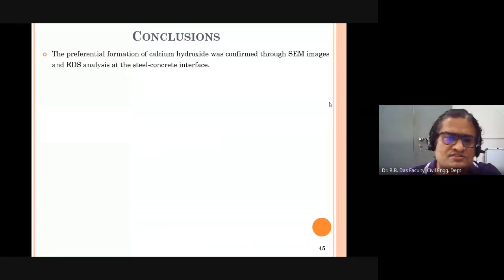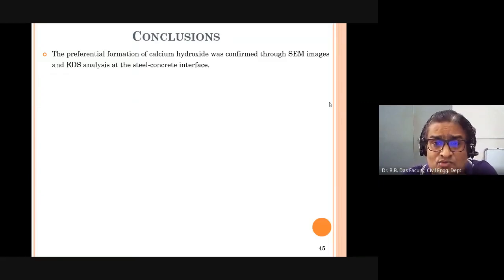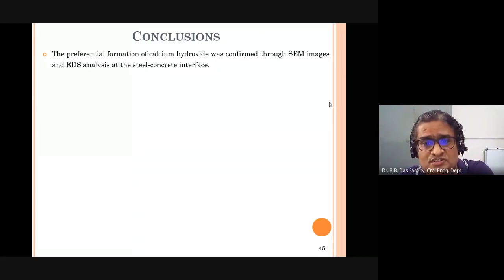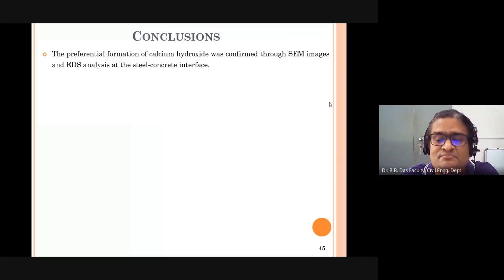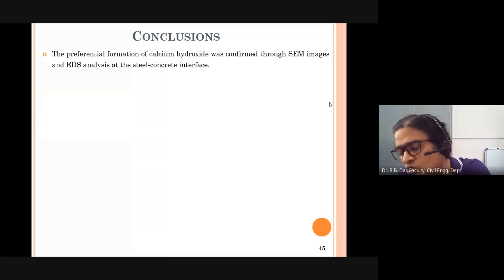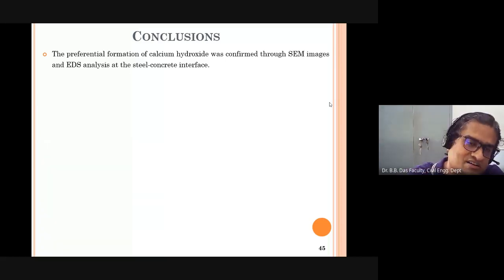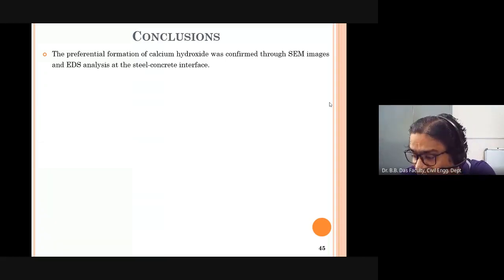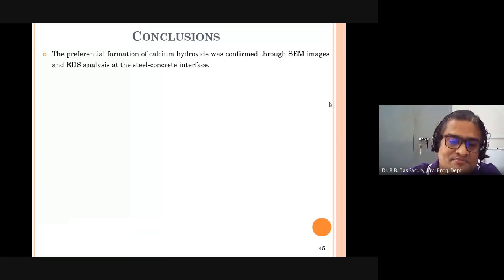So now the conclusions. The preferential formation of calcium hydroxide was confirmed through scanning electron microscope images and energy dispersive analysis at the steel-concrete interface. I was telling you that at the steel interface, my Ca by Si ratio is higher when you go away from the steel concrete interface, so that indicates the formation of calcium hydroxide rather than calcium silicate hydrate.